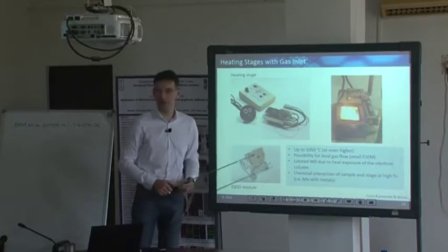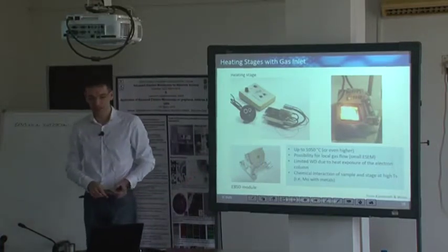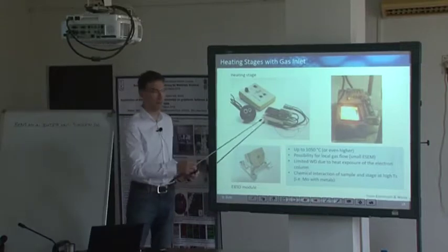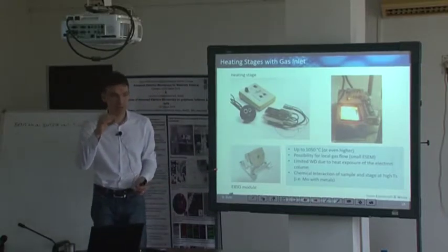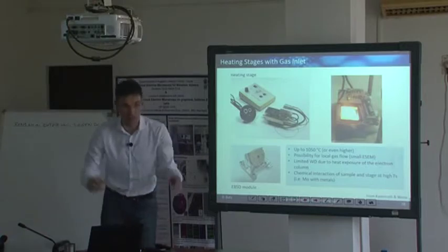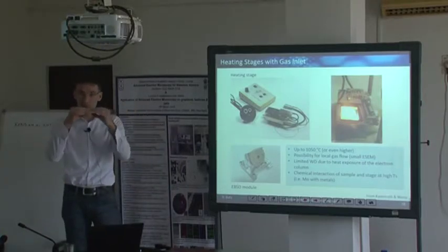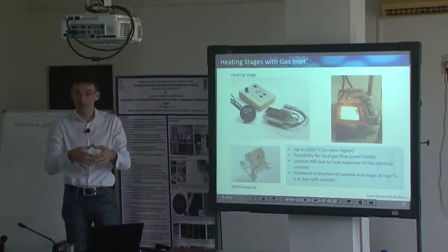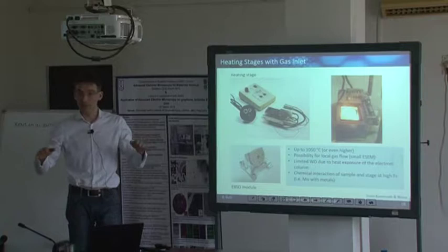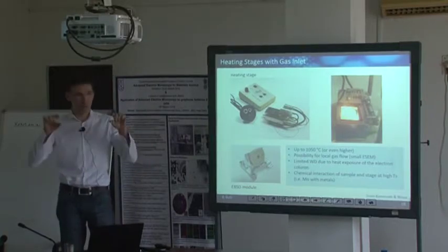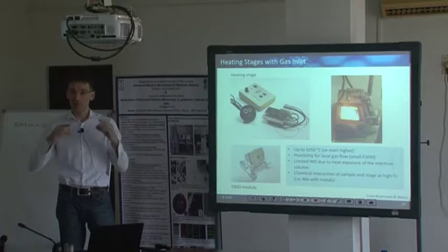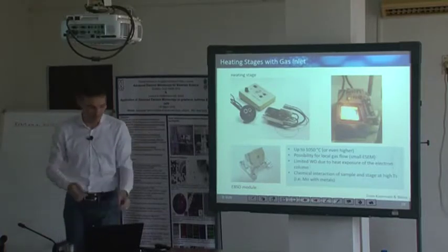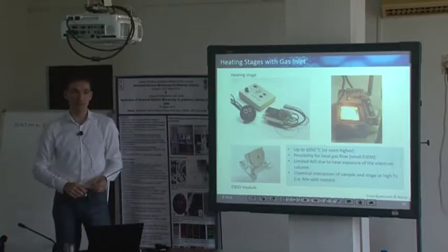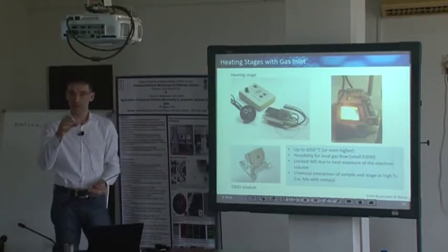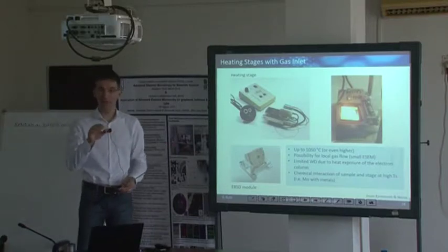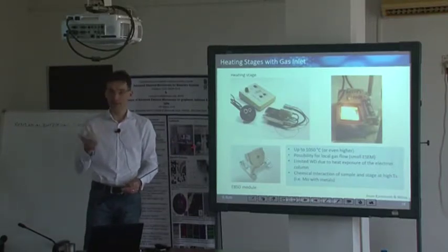And it turned out, as shown in just a few recent publications in the field on environmental TEM, that if you have a very small, very thin TEM sample, you can easily imagine that if you heat from the outside, the heat has to be transported to your innermost region. But in the innermost region, you have a huge surface available to lose energy, and a very limited cross-sectional area available to transport and add energy. So during environmental TEM measurements, the temperature of your region of interest might be off by a few hundred Kelvin from the preset temperature of your heater.